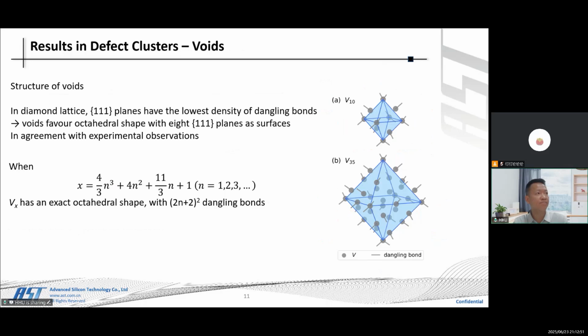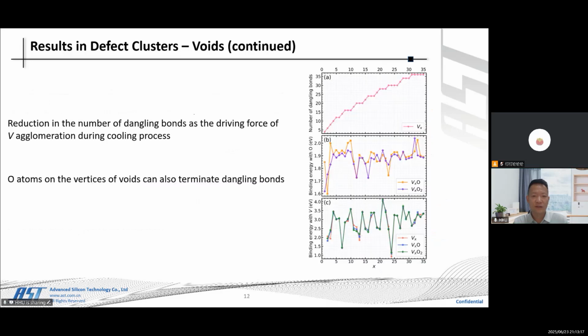There are also defect clusters such as voids. As shown, this is a typical void structure, in a diamond lattice. The void favors octahedral shapes with {111} planes as the surfaces. The reduction in the number of dangling bonds is the driving force of these agglomerations during the cooling process. Oxygen atoms on the vertices of voids can also terminate dangling bonds.